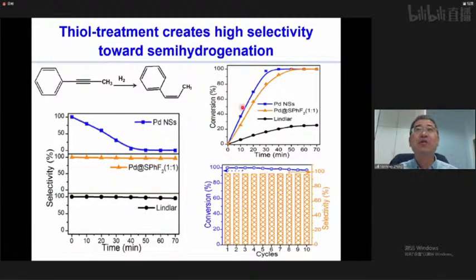Unexpectedly, as you can see here, when we use the highly distorted palladium nanosheets as the catalyst for the semi-hydrogenation of this internal alkyne, we get very high selectivity. We only get these double bond intermediates. I think this is quite easy to understand, right? Because we create a steric effect, and this steric hindrance can prevent the adsorption of these double bond species because they are more bulky. But what is not quite understandable is that we didn't see much decrease in the activity of this catalyst.